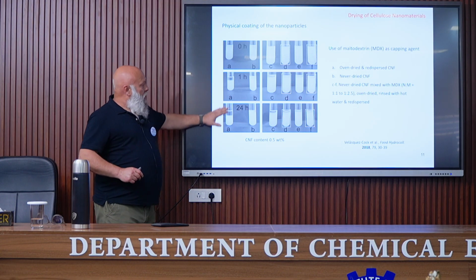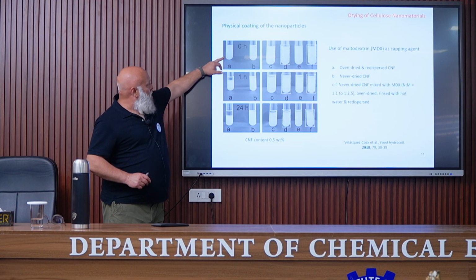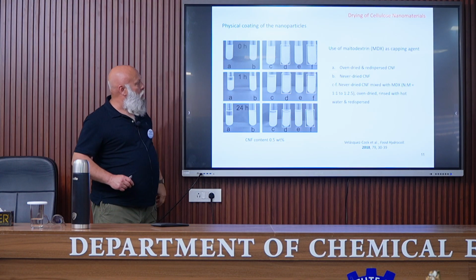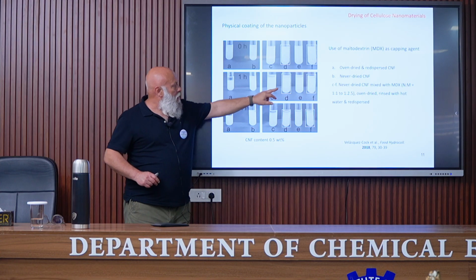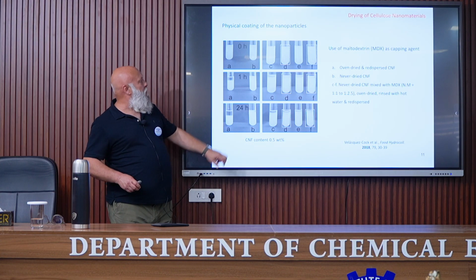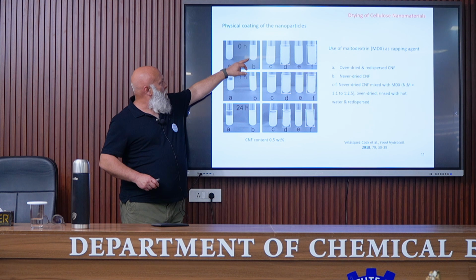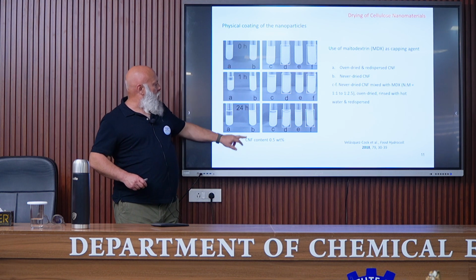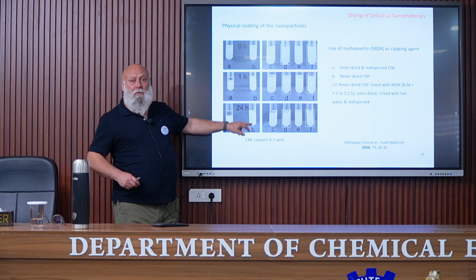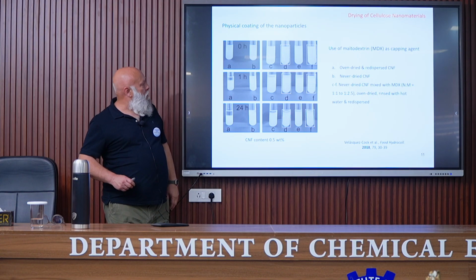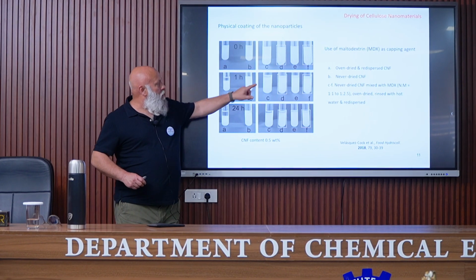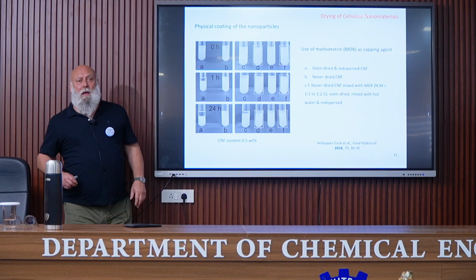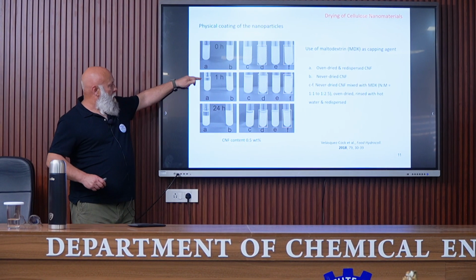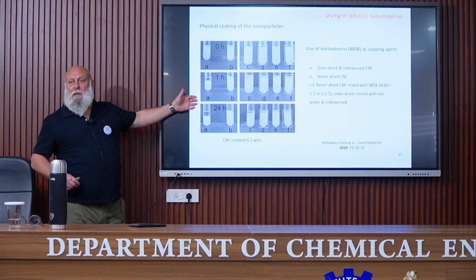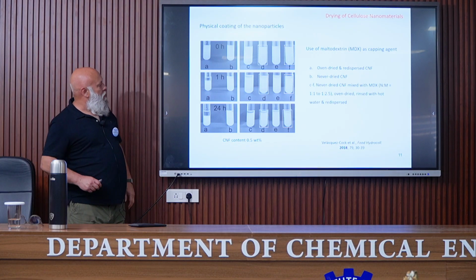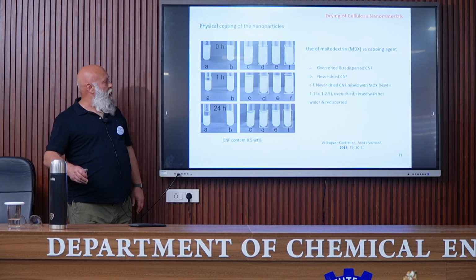So you have here the aspect of the dispersion. So this one, A, corresponds to, sorry, we will start with B. B is a never dry CNF dispersion. At the beginning, after 1 hour, after 24 hours. The suspension is stable. For A, it corresponds to oven dry and redispersed CNF. We clearly see the sedimentation due to the agglomeration of nanofibrils during drying.